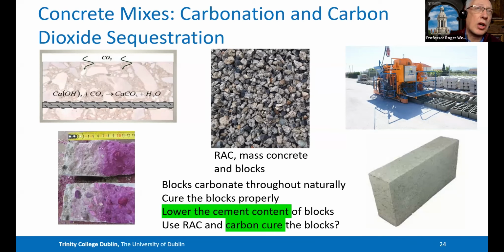So sequestration of carbon for reinforced concrete is very limited. However, as I say, when you crush the concrete and leave it exposed for not very long, it absorbs a lot more. Mass concrete, of course, you can encourage carbon dioxide sequestration if you so wish, because there's no reinforcing steel, and the carbonation doesn't damage the concrete.